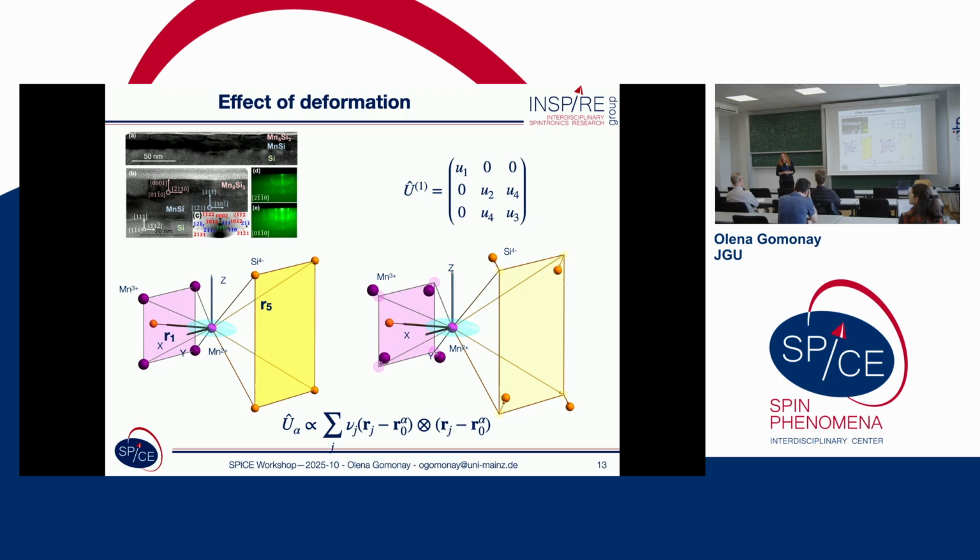I mean, I am a theoretician, but then. No, I know, but I can do the experiment for you if you want. It's very simple. If you have a large unit cell, with soft X-rays you have Bragg peaks in the Ewald sphere, and you can just look at the magnetism. They are as strong as the Bragg peaks of the film. Of course, in the bulk, the ordering that's been reported is not the gamma point, so it shouldn't have an anomalous effect. So it'd be very simple to distinguish these two using elastic resonant X-ray scattering. Okay, good.